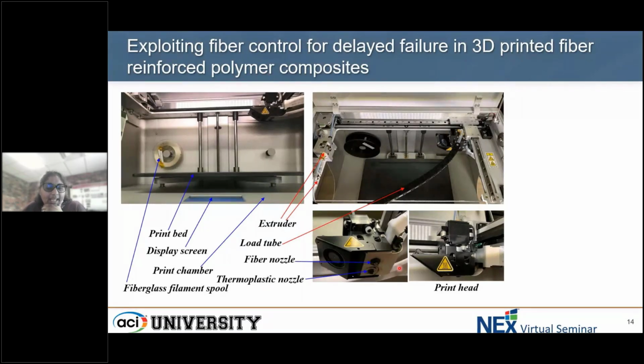Then you have a print head system with two nozzles, which is a fiber nozzle as well as a thermoplastic nozzle. The loading tube itself gets into the print head, carrying both the thermoplastic filament and the fiberglass filament, which respectively come out of the specific nozzles. These nozzles heat to more than 223 C in order to accommodate both the thermoplastic and the fiberglass. For the fiberglass, it's more, which is about 270 C.